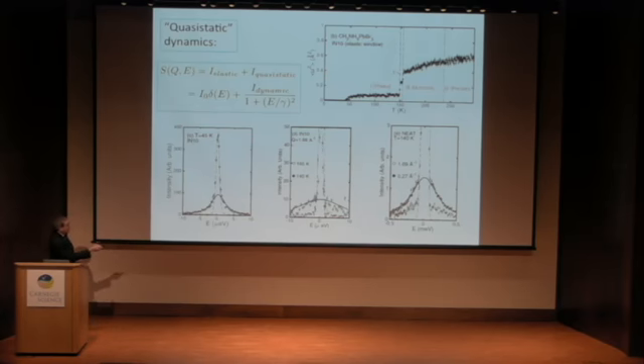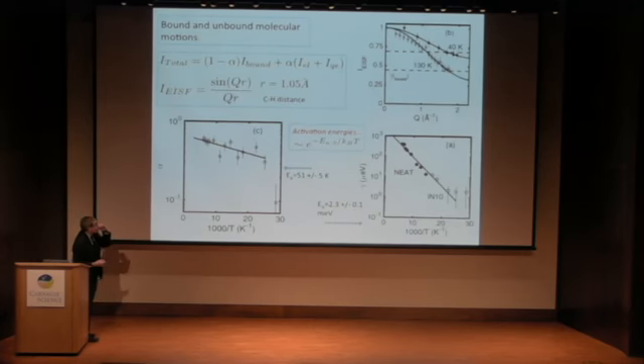However, the funny thing with NEAT is that, once you come up here, and I'll show you why in a few more slides, you lose all of this, and the dynamics completely leave the time window of the instrument. There are a couple of things we can extract from this. First, we can extract the elastic intensity as a function of temperature and momentum, and also the line width of this broad component until this phase transition, where it basically leaves the time window. That's what I summarize in this graph.